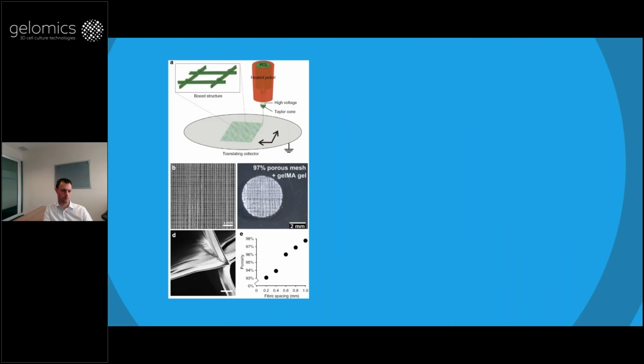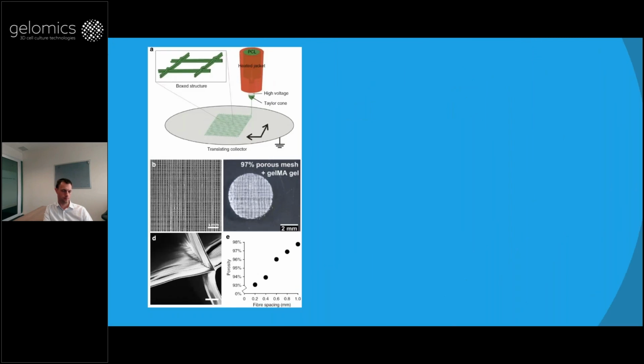Another strategy that we use is fiber reinforcement with melt electrowriting. So by melt electrowriting, we use electrospinning without a solvent, so we get quite a stable jet and collect this on a computer-controlled collector. So you get fibers in the tens of micron-sized range. These scaffolds have really high porosity, so you need only a few % of polymer to create a scaffold, which is a bit different from the typical FDM fused deposition modeling scaffolds, which have much thicker struts and also lower